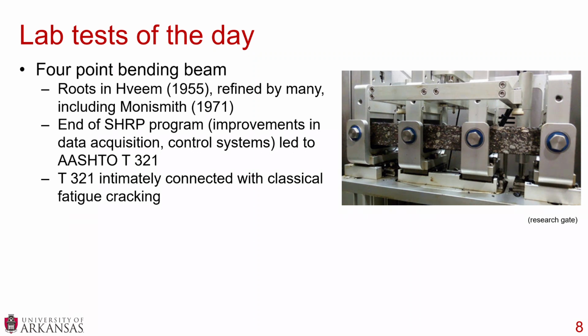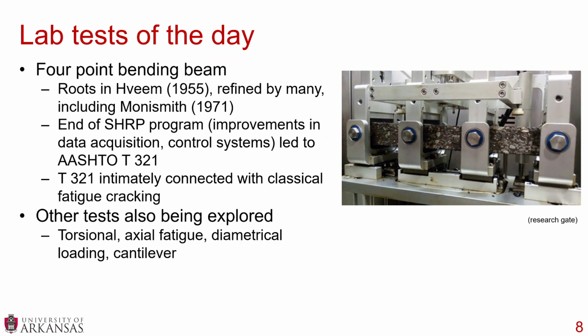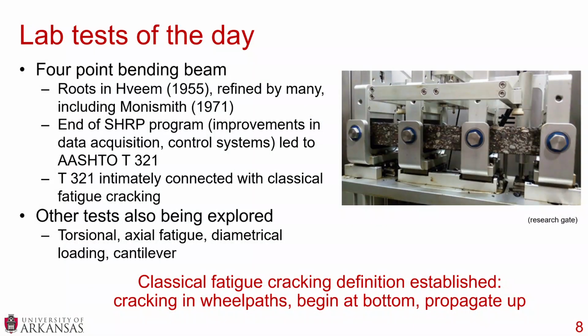It's gone through a lot of iterations, it's gone through a lot of improvements, but AASHTO T321 is intimately connected with classical fatigue cracking. Now, there were other tests also being explored that never really gained as much traction. That included torsional tests, axial fatigue tests, diametric loading, and cantilever. But at the end of the day, the 4-point bending beam test is intimately connected with classical fatigue cracking. And the definition of classical fatigue cracking is you have cracks in the wheel paths. Those cracks begin at the bottom of the pavement structure and they propagate up. So this is all a summary of classical fatigue cracking.